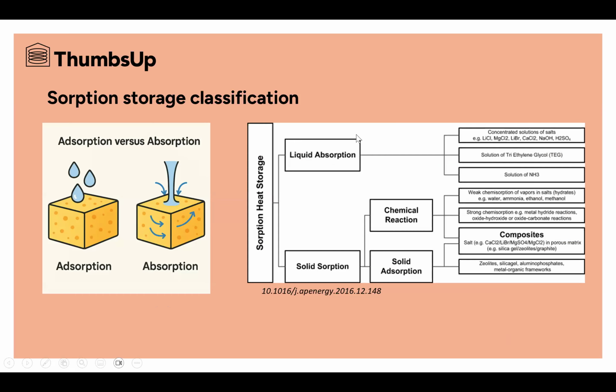Sorption storage materials can be classified in solid sorption and liquid sorption. In particular, solid sorption can be divided into two other categories: chemical reaction and solid adsorption. An example of liquid absorption is a concentrated solution of salt, for example, lithium chloride, magnesium chloride, or calcium chloride. Another example, for solid absorption, is composite material, which is the case of the ThumbsUp solution. In particular, in the ThumbsUp project, we used a composite using silica gel as a porous matrix, impregnated with calcium chloride.